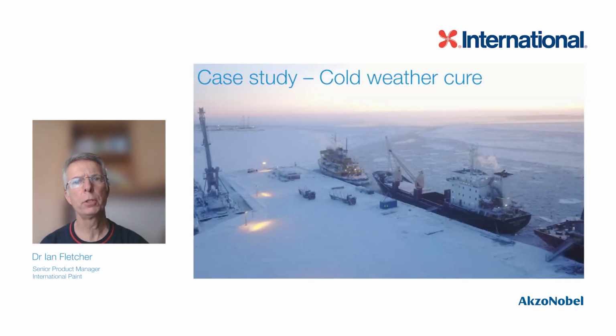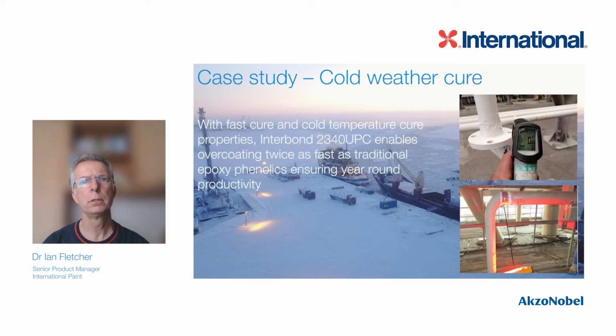The slow curing of traditional epoxy phenolics can have unexpected consequences. The pipe spool coating project that was being carried out in the winter required the paint shop to be heated to 15 degrees Celsius. An epoxy phenolic was applied during the day, but then the paint shop heating system was turned off overnight. This caused the shop temperature to drop and the epoxy phenolic coating to remain wet the next day. The painting schedule was then delayed by 48 hours whilst the pipes were moved to another heated room. After forced curing, the coating surface required extra washing and then abrasion to clear coating contamination after moving the pipe spools. Overall, an extra week was added to the coating schedule, as well as increased labour and heating costs. Had Interbond 2340 been used, none of this would have happened, and the shop could have maintained its productivity.